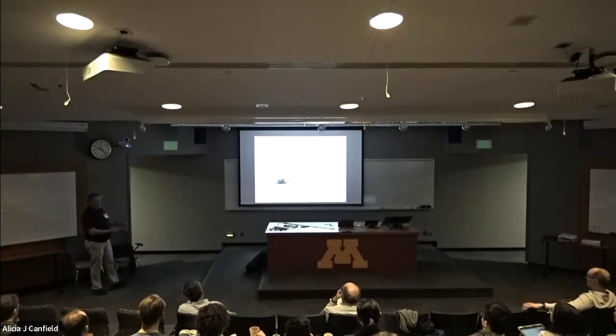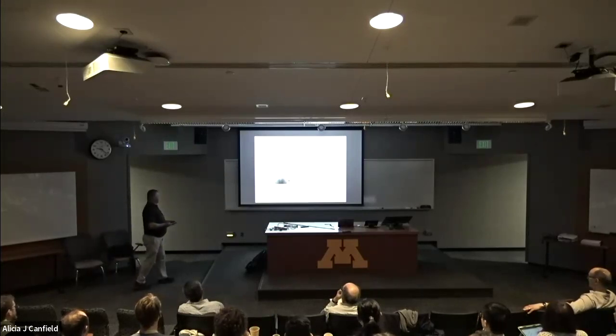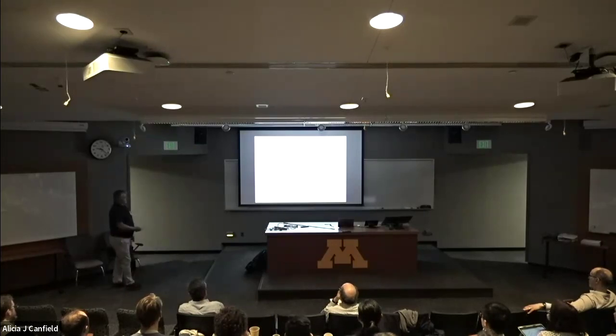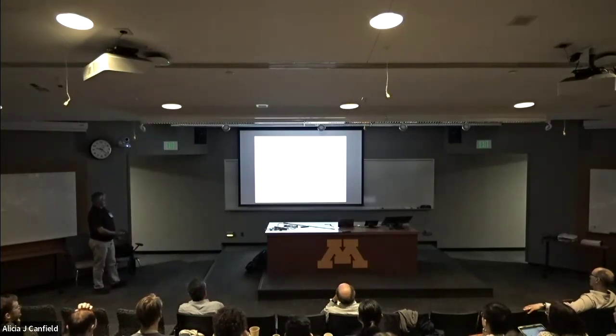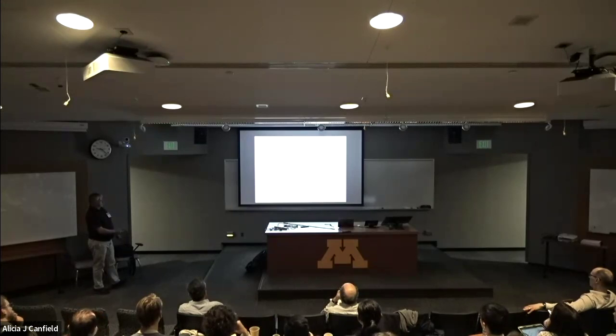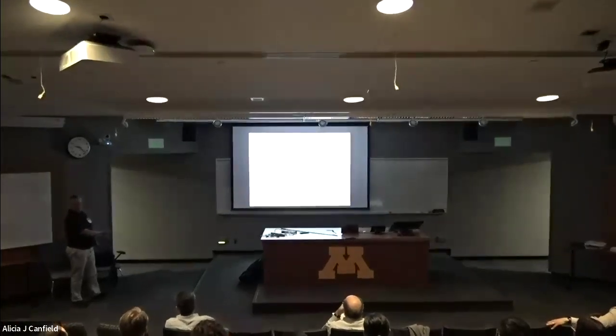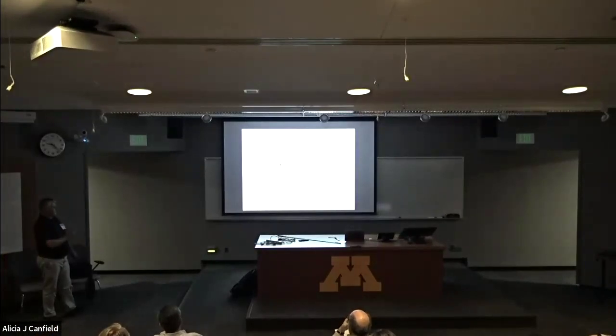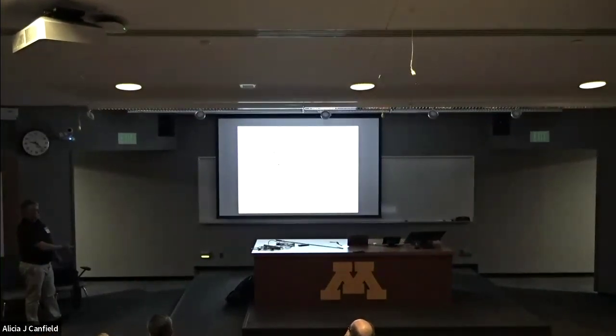So these are kind of make-you-feel-glad-to-be-alive sort of data. It's the experimental data. The other really interesting thing, I should say, is the impressive work that's been done by a graduate student in my group, Veronica Sunko. She noticed that the surface states, which also exist because it's not a charge neutral surface, those surface states are strongly Rashba split, but not when the surface is terminated by the heavy metal. It's when the surface is terminated by the transition metal octahedra, and then you've got a problem with your intuition.